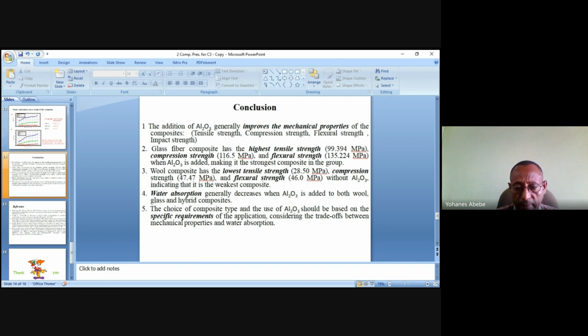In addition, the glass fiber composite has the highest tensile strength, 99.394 megapascal. The compression strength is 116.5 megapascal, and the flexural strength is 135.24 megapascal when alumina is added, making it the strongest composite in the group, the glass fiber composite. But the wool composite has the lowest tensile strength, 28.5 megapascal for tensile, compression strength 47.47 megapascal, and the flexural 46 megapascal without alumina, indicating that it is the weakest composite.